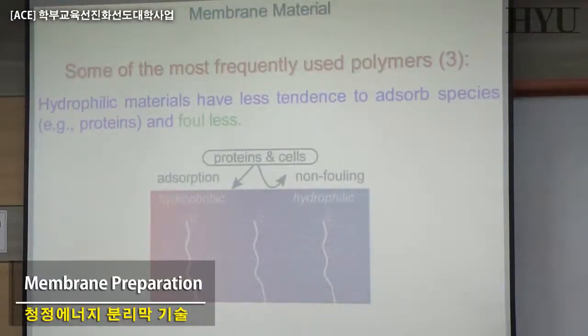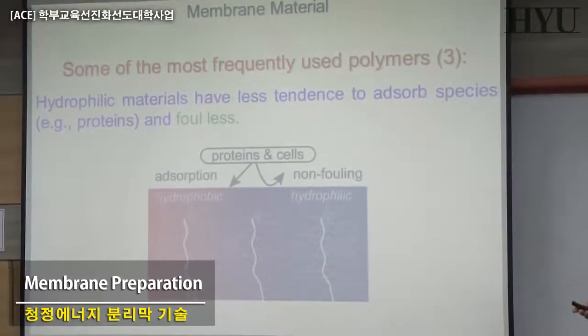If you go to the north of Spain, in León, there is a company producing antibiotics. For many years a lot of the work there was done by ultrafiltration. But the main problem is to control the adsorption of the protein on the membranes. So you have to find a way to increase, as much as possible, the hydrophilic character of the membranes working with antibiotics, because that minimizes the adsorption and makes the control of the fouling easier. And then you have to do what has to be done for this.